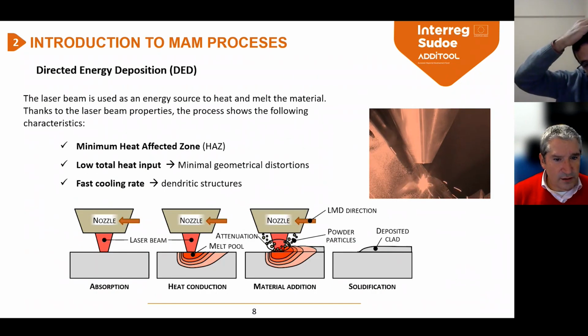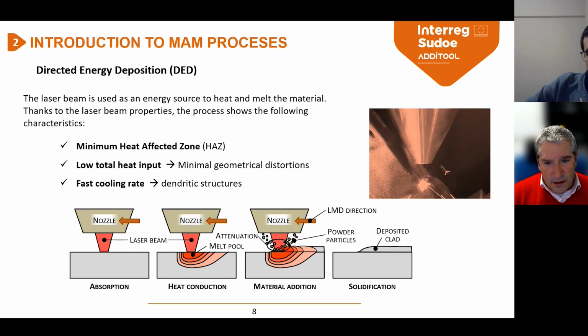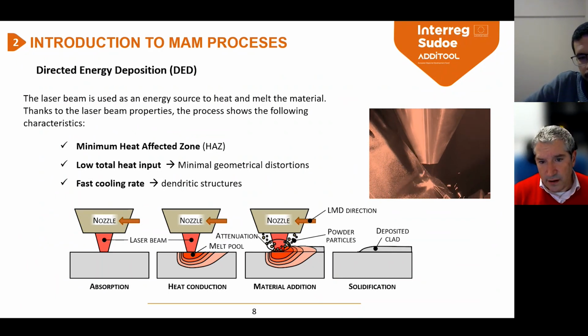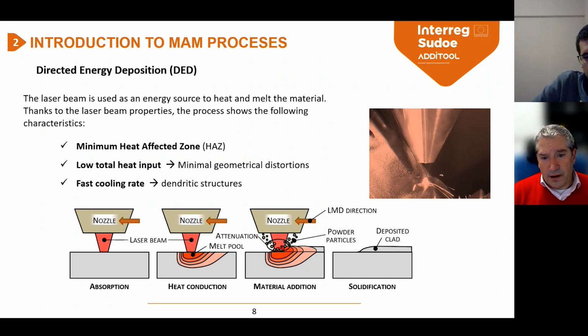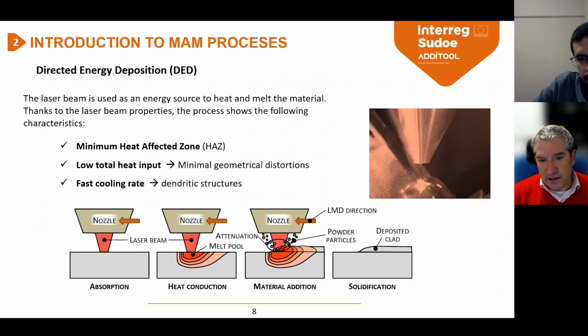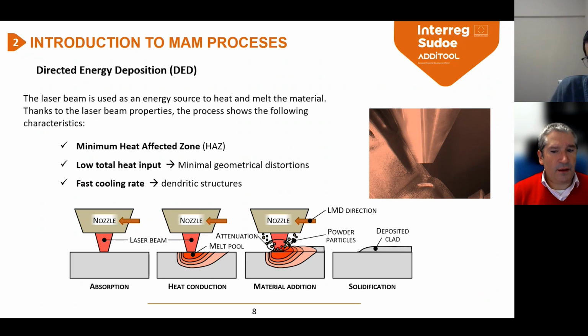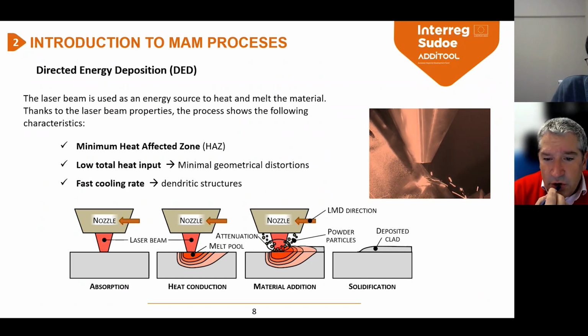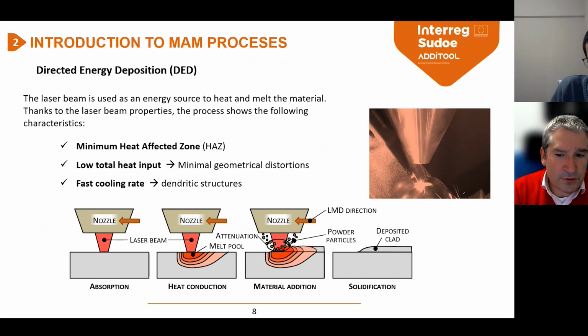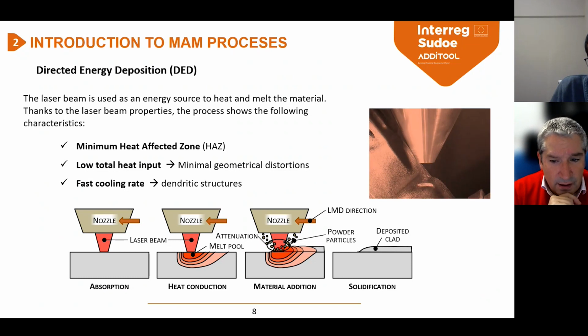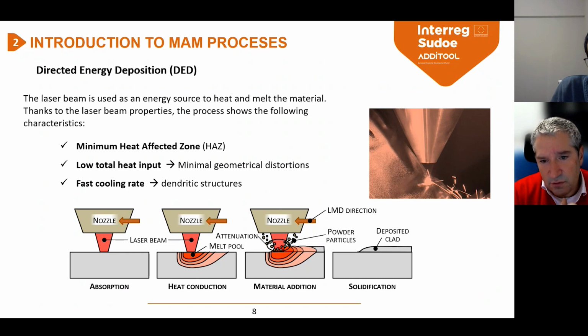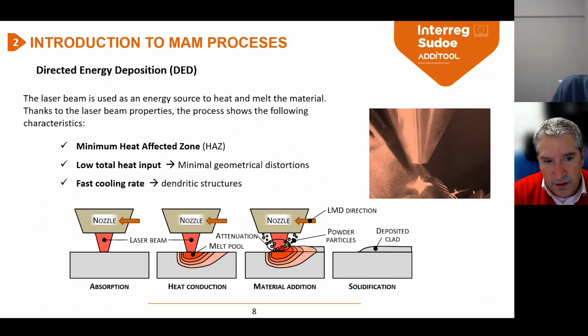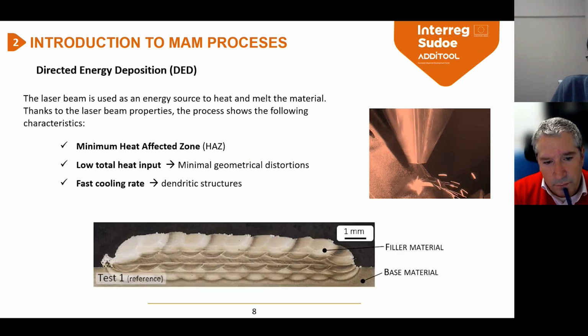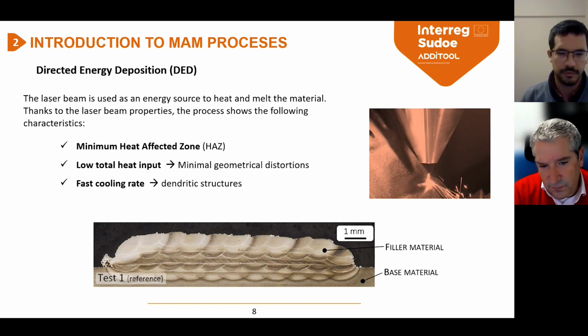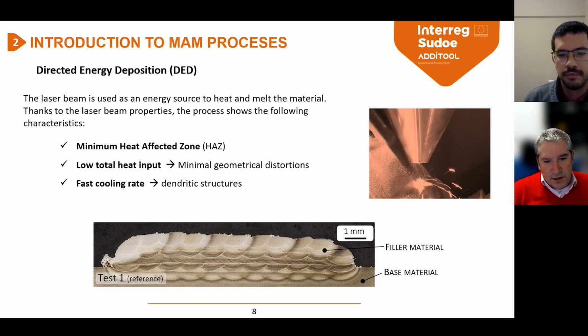On the other hand, the other process, direct energy deposition, here you can see in the video, the idea is that with a system, in that case a nozzle, we inject material. It can be either powder or wire, in combination with an energy source that can be a laser. We melt a substrate, a previous part, and then we inject the material into the melt pool that we have created in the substrate. So we can deposit material in an area, and by overlapping the tracks of the deposition of the material in a layer, we can coat a surface, and we can even go layer by layer in order to build. Here you see an example of a layer by layer sequence that we have built as a feature.